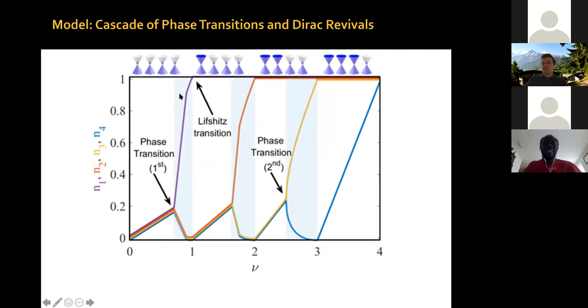But we can tell you that at least for filling factor 1, when you fill the first flavor, this is a spin flavor. So there is a magnetization, the system is spin polarized at filling factor 1. The system decides to put all of the electrons, by the time you reach filling factor 1, with the same spin in your magic angle graphene. What happens at filling factors 2, 3, etc., can be a little bit more complex, and it's still being investigated. We have new data suggesting that interesting things happen there. So now,